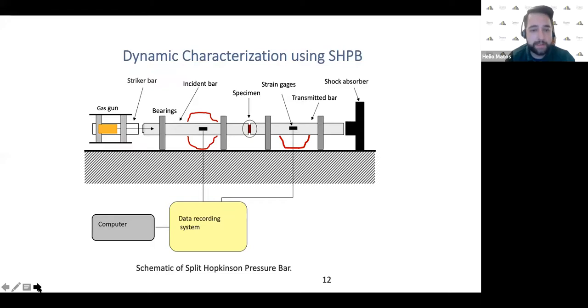What is shown here is a specimen in compression between 2 bars. So we have a striker bar that sends a pressure pulse that interacts with the specimen that is sandwiched between the incident and the transmitted bars. But we also have the same pressure bars that can do tension and torsion experiments. In addition to that, we can have specimens being cooled or heated between negative 40 Celsius and 1,200 Celsius for metallics.